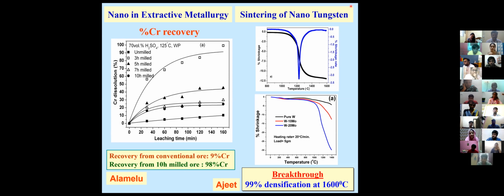So what we have simply done is take the tungsten powder and ball mill it for about 2 to 3 hours, and that tungsten is now a nano tungsten, and you can sinter it at 1600 degrees centigrade, as low as 1600, which is still high for some of the applications. But when you compare with 2800 degrees centigrade, the energy that you need to spend is going to be much lower when you are able to sinter it at a much lower temperature. So this is something in Trichy.